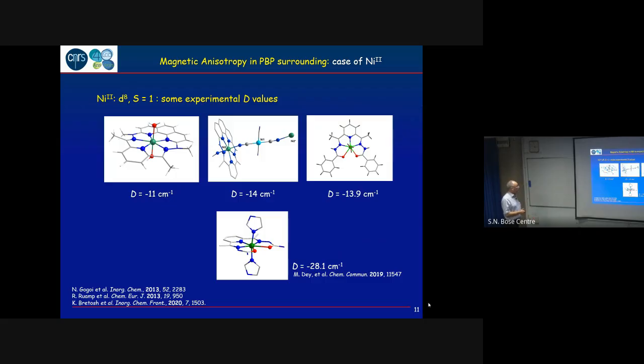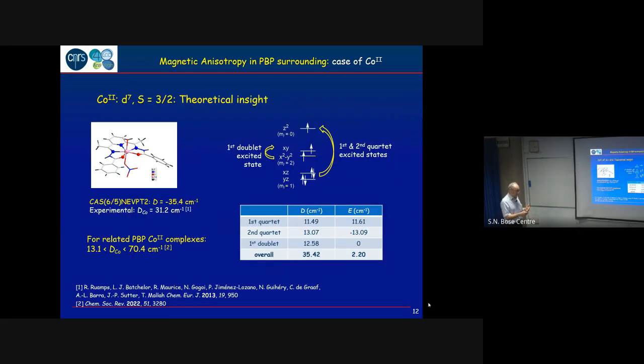Okay, so far for nickel. If you go to cobalt, you can do exactly the same analysis. And if you do that, what you will realize is that all excited states will have a positive contribution. This has been again confirmed by the theoretical insight. And for such a complex, usually the expected anisotropy is around 35.